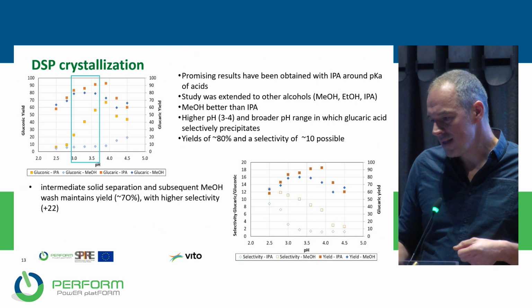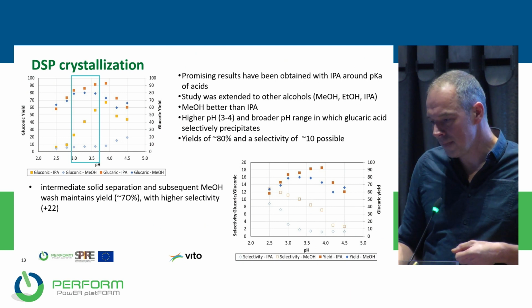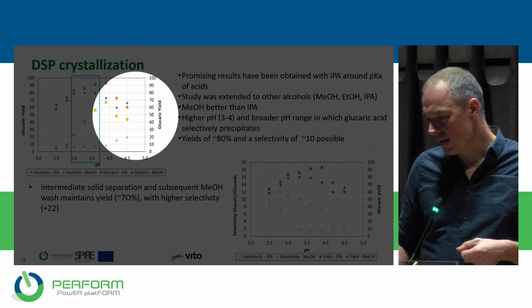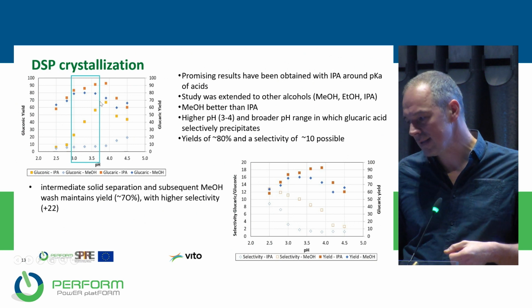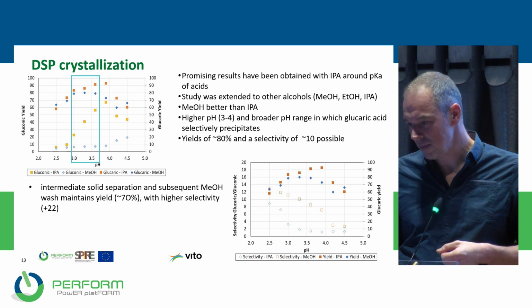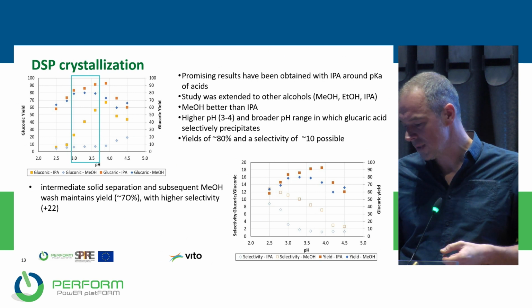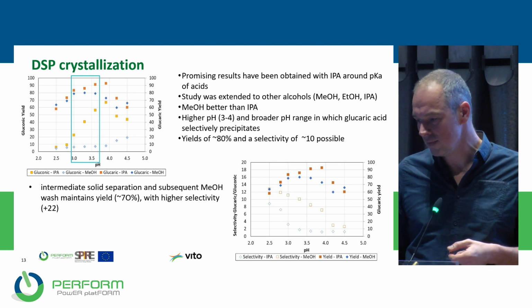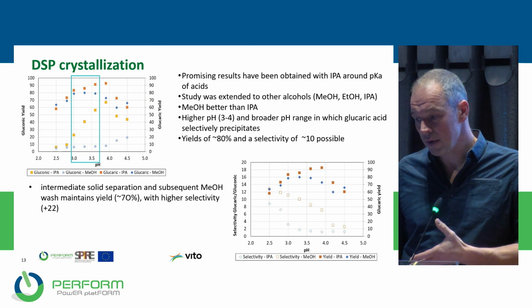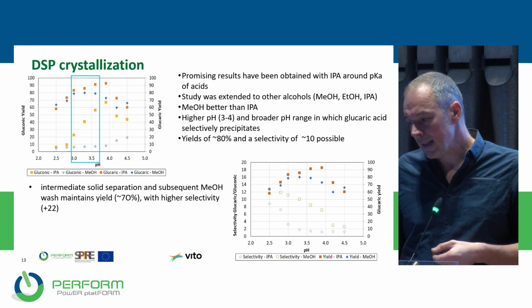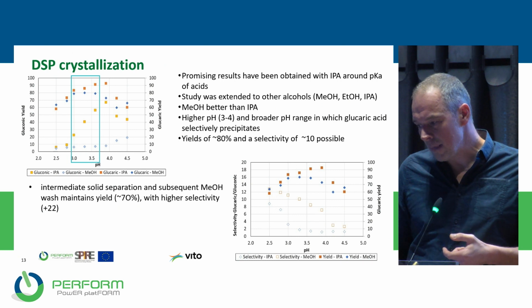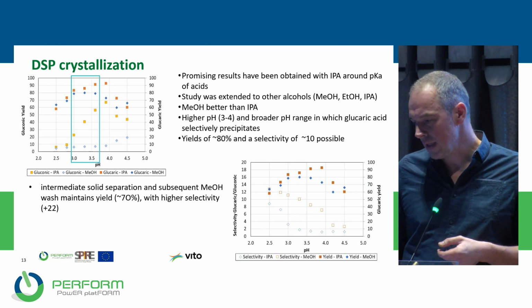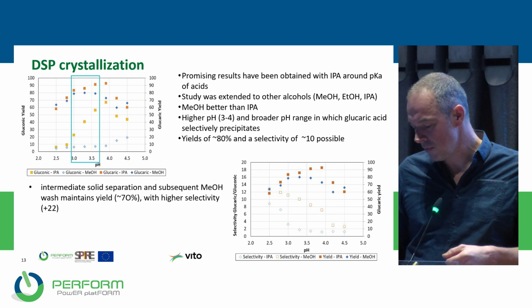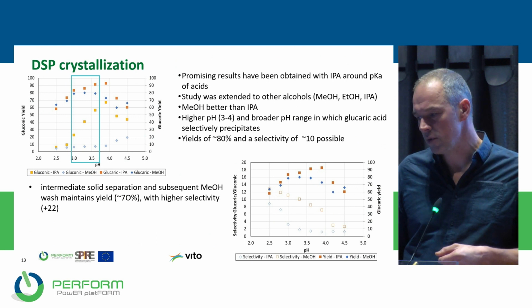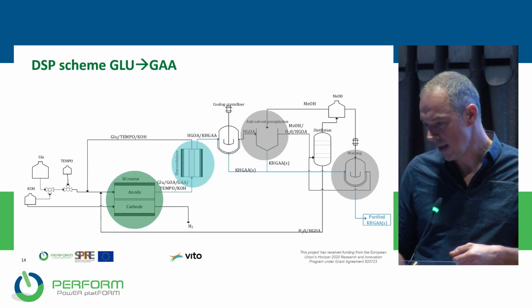This actually shows the effective separation, so the yields of gluconic and glucaric, when we added the anti-solvent precipitation. So the crystallization in this case was enhanced by adding an anti-solvent, and the anti-solvent here, which worked best, was methanol. So methanol actually proves to be a very good way of also further refining the produced monoglucarate crystals.